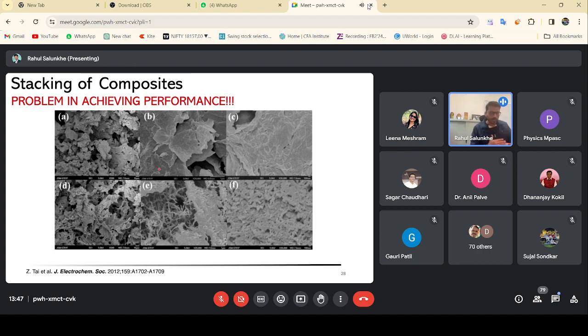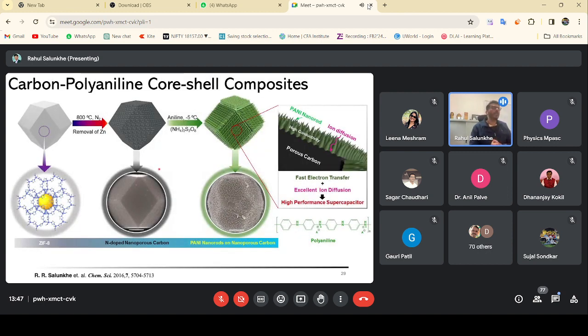When we coat the material on the surface of the plate, the material gets stacked on the surface, and because of that the ions cannot access the material very easily. Because of this stacking problem, most of the materials' performance gets degraded when they are coated on the stainless steel substrate or any current collector. So this was the basic problem. To avoid this problem, we have utilized our nanoporous carbon.